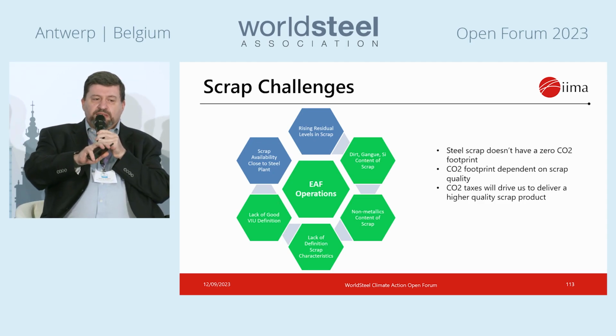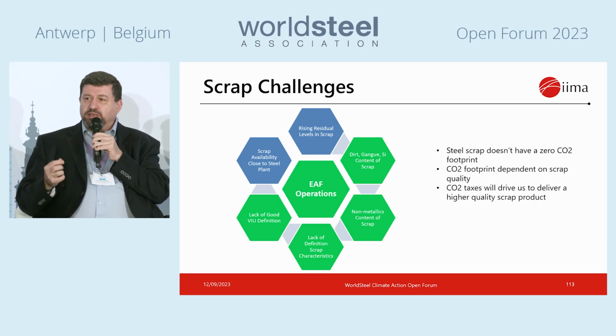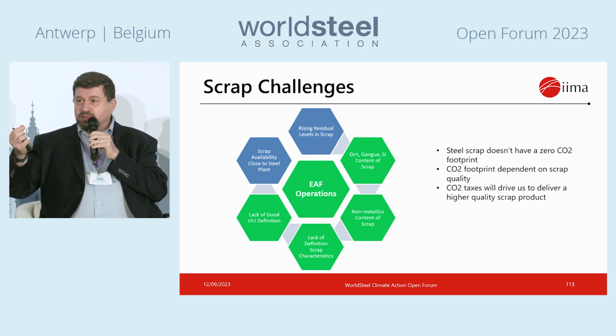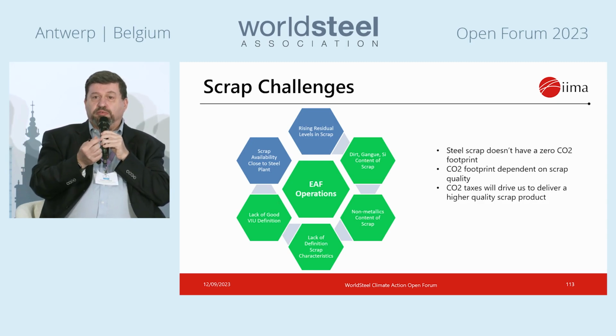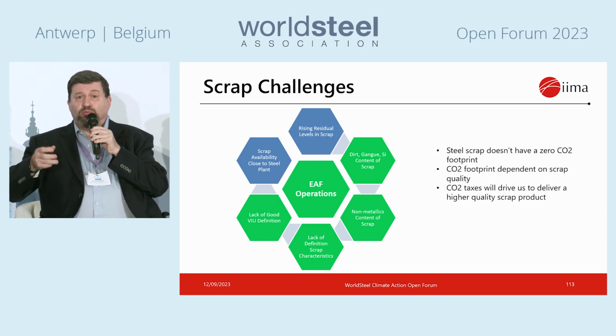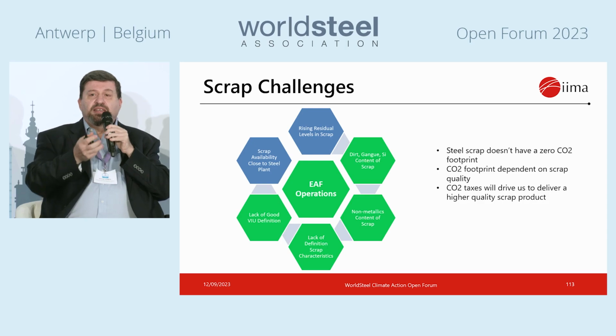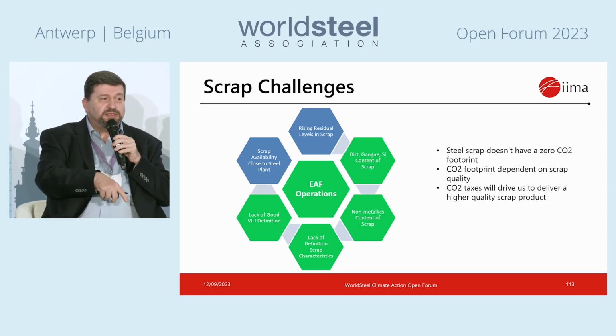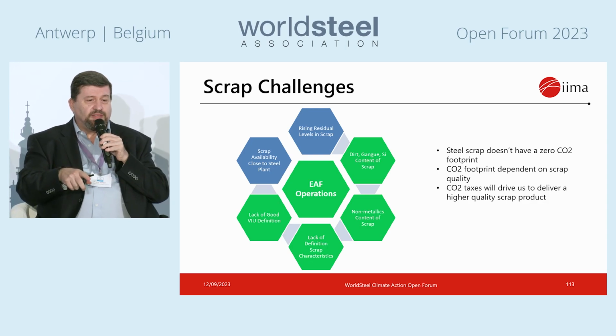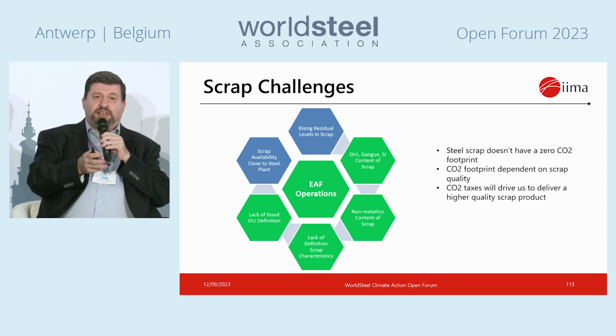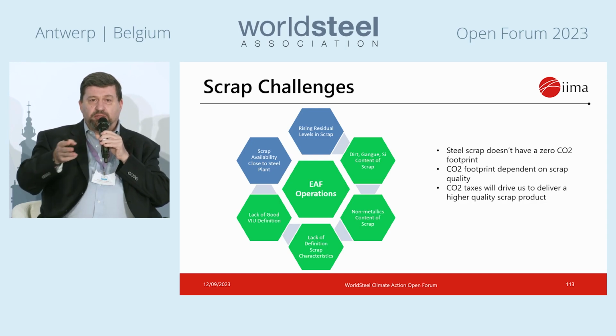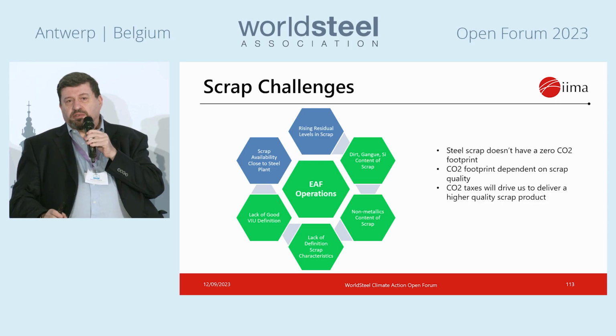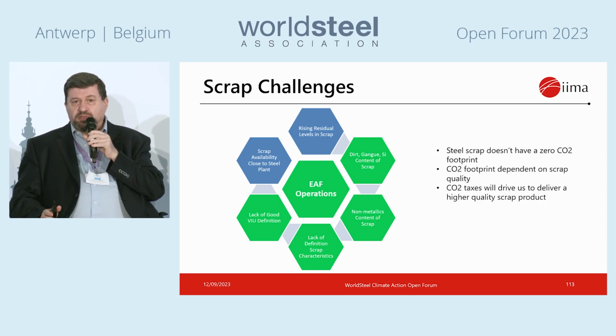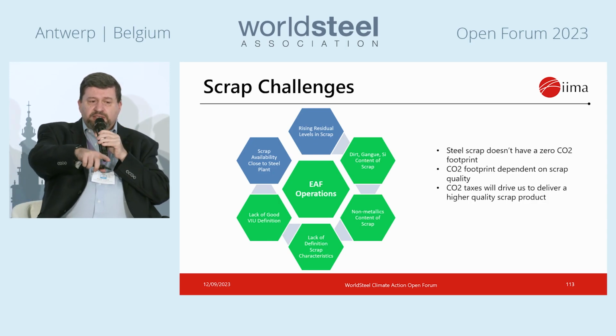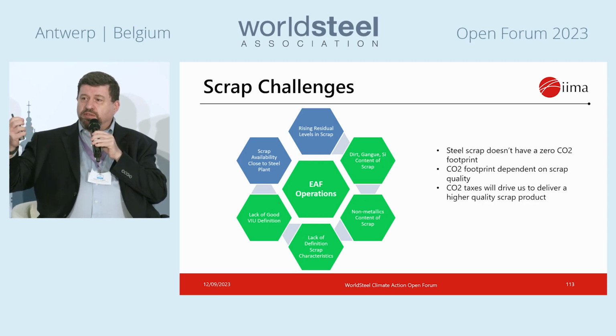But when we look at rising residual levels in scrap, we have to differentiate between contained copper and free copper. So free copper is things like when I shred an automobile, I have copper wires and other things in there. It gets mixed in. It ends up going into the furnace. It gets melted. Now it's in the steel, and I can't get rid of it. But we have technologies now implemented both here in Europe and also in North America where we can effectively produce shredded scrap at about a 0.16 copper consistently. So that's very important.